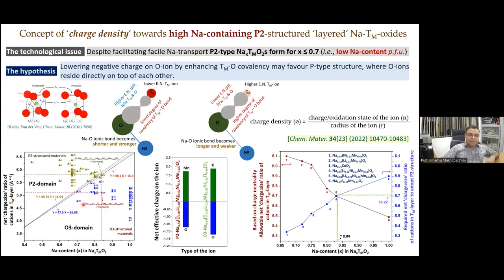Now, when we looked at a lot of literature published with compositions pertaining to the P2 type structure and the O3 type structure, we figured out that they can actually be segregated based on the charge to size ratio of the transition metal slab.